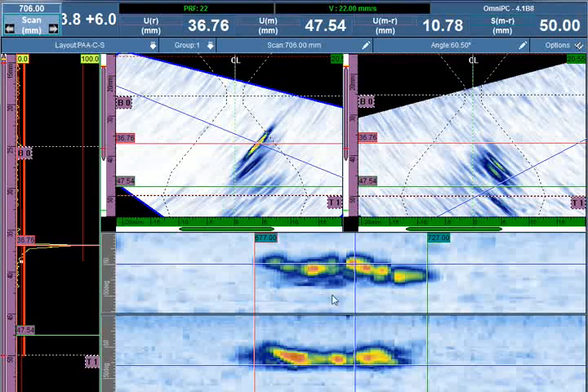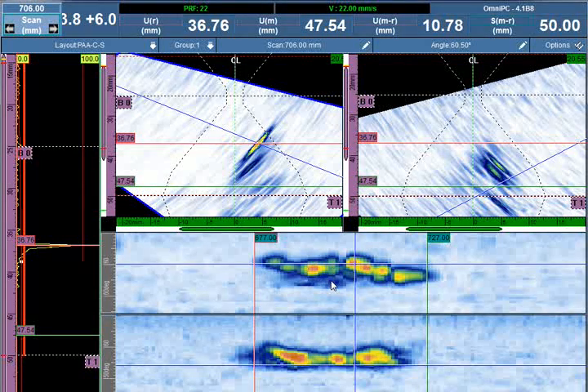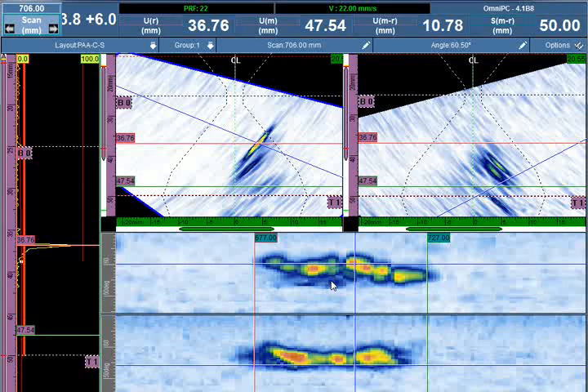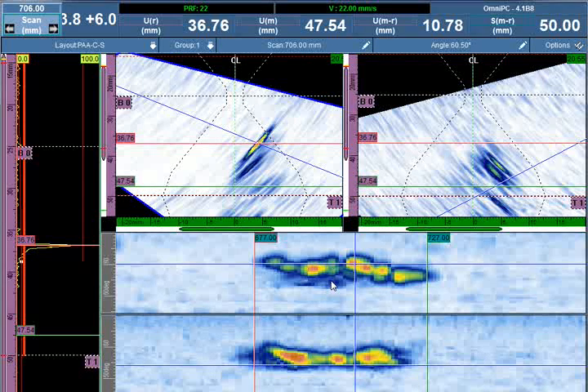Shear wave tip diffraction is most beneficial on crack-type indications where the ligaments are smaller than the beam size. Amplitude drop is most beneficial where there is favorable orientation — near perpendicular — typical of weld bevel flaws such as lack of fusion.